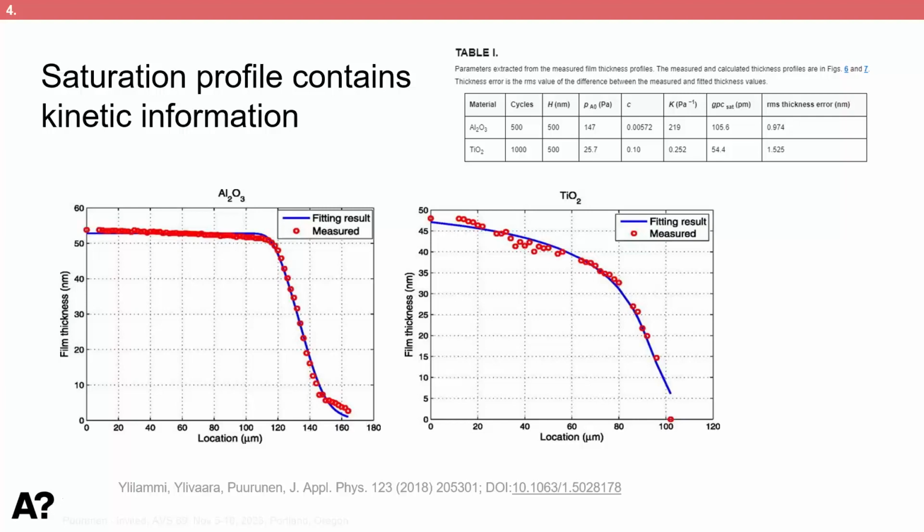And he was able to fit TMA water results, getting a sticking coefficient of 0.00572 and an equilibrium constant for the adsorption. So this assumes also reversible reactions, of 219, and this is signifying pretty much irreversible reactions. This is a high value and it corresponds to basically irreversible reactions.